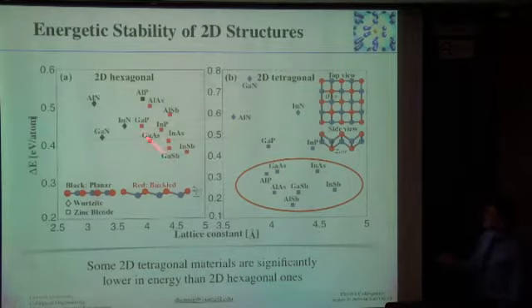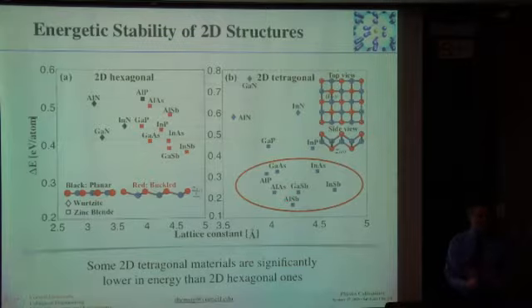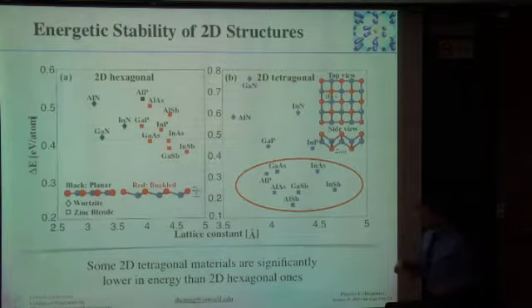So I'm showing you here, this is the same data I showed you before, the hexagonal structures, flat or buckled. These are the tetragonal ones. And if you look at the energy scale, we go down all the way to something like 0.15 electron volts. So they're close enough to the 3D crystal structure that they might actually be easily formable in an experiment.